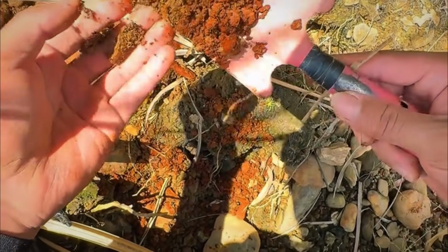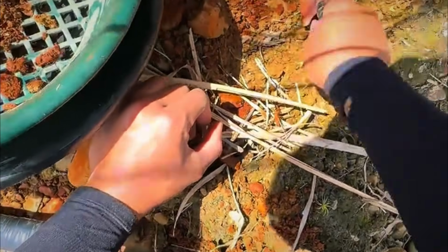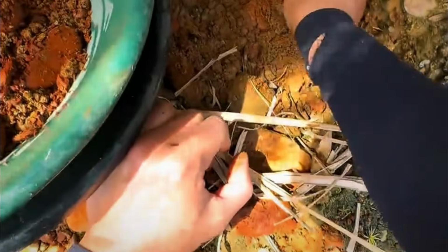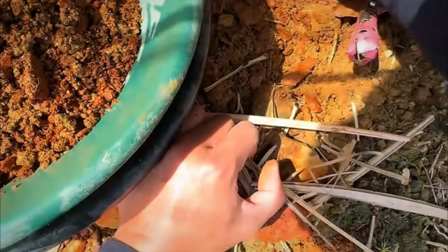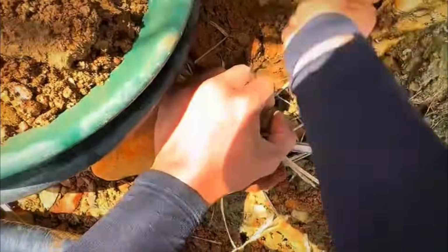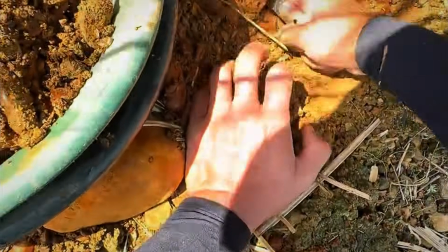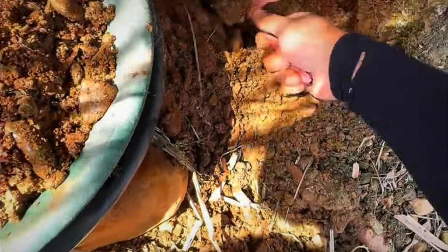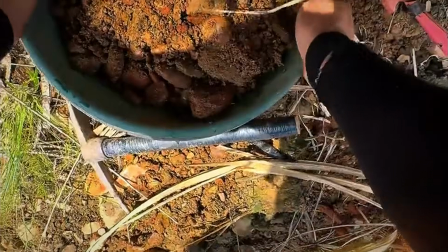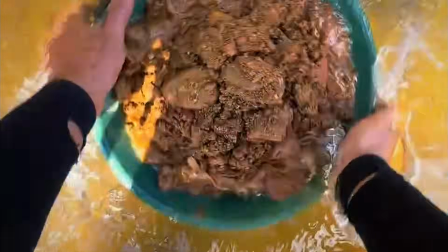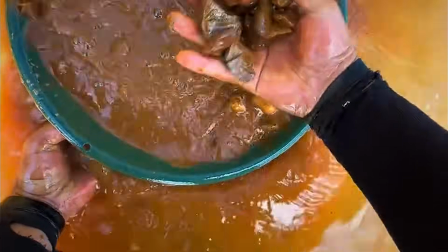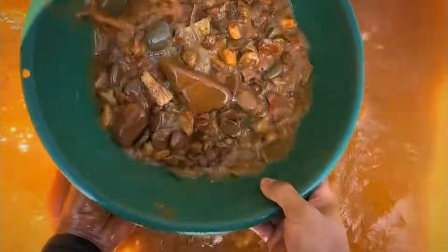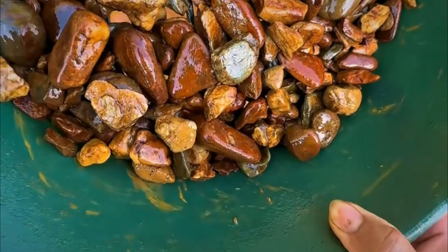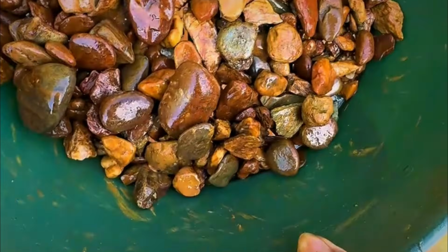If repeated pans from different parts of the same vein or float yield a black or brassy concentrate that doesn't wash away and resists magnetic removal, the gold may be refractory, locked in sulfides, and an assay becomes the only way to confirm its value. In systems with visible gold, the bar is lower. Even a few unmistakable flakes in hand-sampled quartz justify assay, especially if found in multiple locations. A general rule of thumb: if you recover more than 0.1 gram from a single fist-sized rock via panning, that sample may exceed 20-30 grams per ton, g/t, a commercially significant grade, particularly for underground mining.